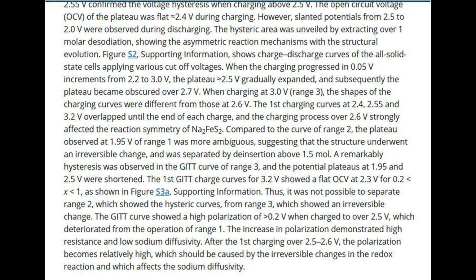Thus, it was not possible to separate range 2, which showed the hysteretic curves, from range 3, which showed an irreversible change. The GITT curve showed a high polarization of greater than 0.2 V when charged to over 2.5 V, which deteriorated from the operation of range 1. The increase in polarization demonstrated high resistance and low sodium diffusivity. After the first charging over 2.5-2.6 V, the polarization becomes relatively high, which should be caused by the irreversible changes in the redox reaction and which affects the sodium diffusivity.